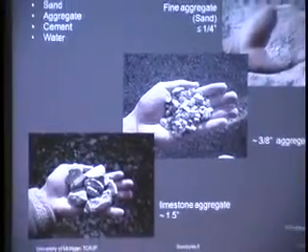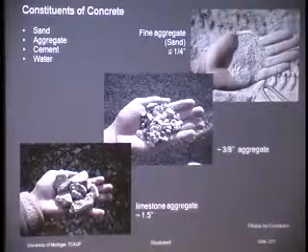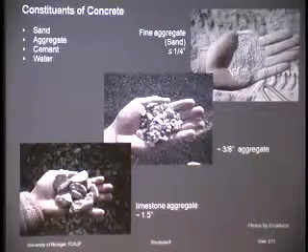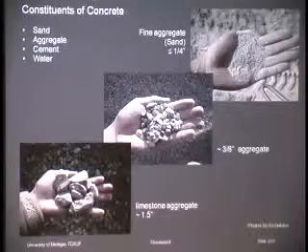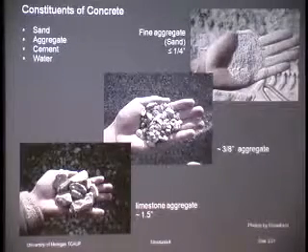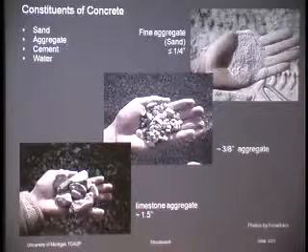So that's an advantage of this crushed rock. Also, you get an idea of the grading. Usually in architectural work, because of the size of the members and the placement of the bars, 1 inch or 3/4 inch is probably the maximum size. If it's a really big member, you might get a little bit bigger. Aggregate like this, I don't know for sure what this is, but it looks like 1.5 to me. That's definitely a pretty large piece.